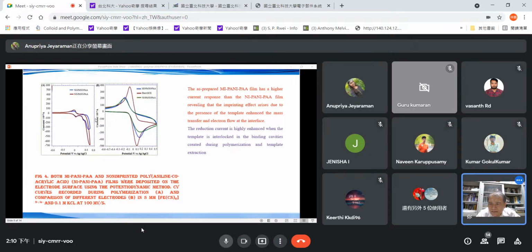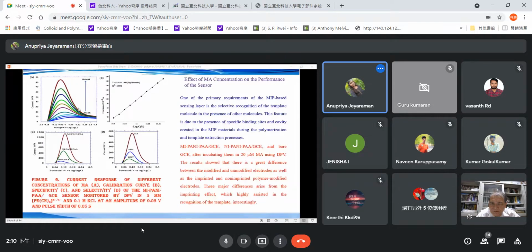Yeah, currents, okay. CV was carried out. Here, this is for non-imprinted melamine, you see very low conducting. This is the melamine composite, which forms high conducting. This is the ferricyanide system, carried out similarly. This blue line is the molecularly imprinted polymer, here you see high current. LOD, sensitivity, specificity, and selectivity were carried out in DPV analysis, where the imprinted polymer exhibits.